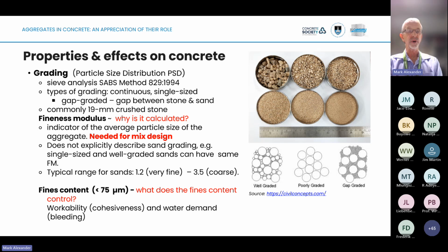Okay, now some of the properties of aggregates and their effects on concrete. First of all, grading. Grading is important. We can grade our aggregates. We use the sieve method. And in general, in South Africa, we tend to use what we call gap-graded aggregates. We do occasionally use continuous grading. And the little diagrams on the bottom right would show you some of that. In the gap-graded aggregates, there tends to be a size gap between the stone and the sand. So maybe 19 millimeter stone, and then the sand particles down at 4.75, and there's something missing in between. And that's largely because, again, of our aggregate sources and what we can do practically. It's possible to do continuous grading, but it's only used in particular cases.